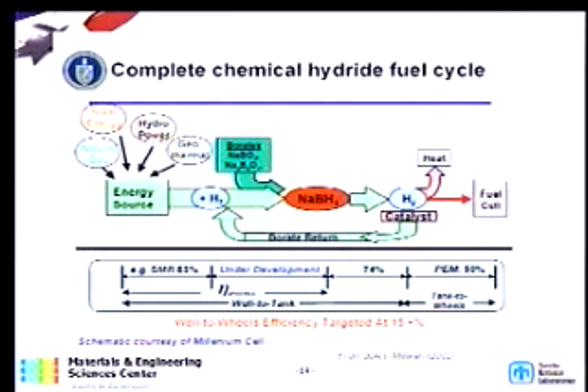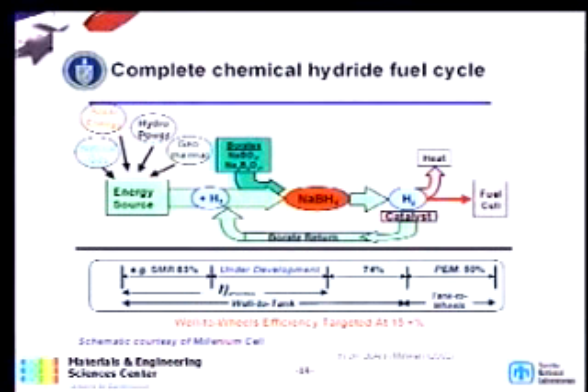For example, you use all this renewable energy to generate hydrogen and hydride the sodium borate, and then you go through and use a catalyst with water and generate hydrogen. If you haven't seen this Millennium website, they show a very nice video that with their catalyst, you can see the hydrogen generation stop right away if you take the catalyst away. It's very, very attractive. But the trouble is the cost. If you consider gasoline at like $1.50 or $2 a gallon equivalent, this system costs at least $50 or more.